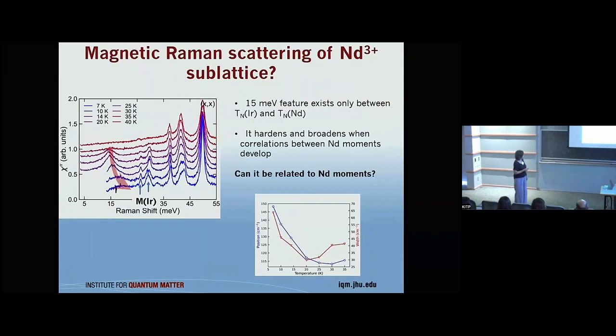The next thing took us a lot of time to figure out. We have this very strong excitation which comes up at the temperature where iridium orders, but the iridium order doesn't change down to low temperatures, while this excitation changes dramatically as we cool down. It broadens and shifts to high frequency, so it's like an anti-soft mode. There were various discussions about what it could be, like a sublattice soft mode. No, it cannot be, because if it's a soft mode, then it goes down in frequency and broadens. This one goes up in frequency and broadens.